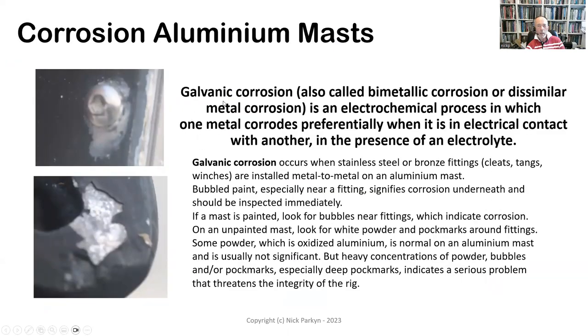Galvanic corrosion in masts, we spoke about that, and this is an indication of how and where we might see it. You see this kind of powdering effect, or you see the paint actually flaking off because corrosion has occurred beneath it.